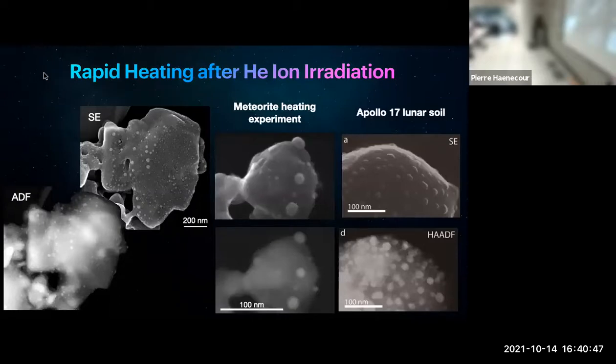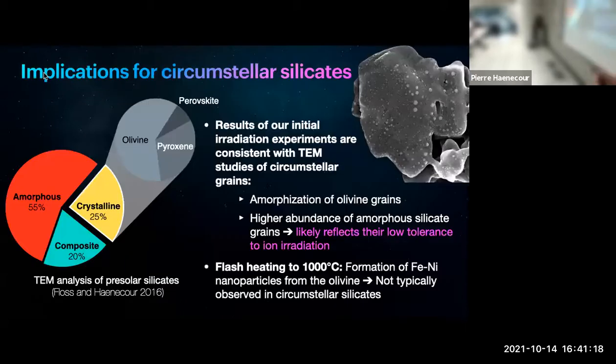So compare what we see in our experiment. That's what happened to our sample, both in transmission and on the surface, compared to what we found with our meteorite experiment. It's an image of one of our heating experiments that we did here at U of A, compared to what was observed on Apollo 17 lunar soil, showing you the exact same texture that we can form by flash heating the sample. So flash heating is very typical of what you can observe here and what we can even observe on the surface of the moon.